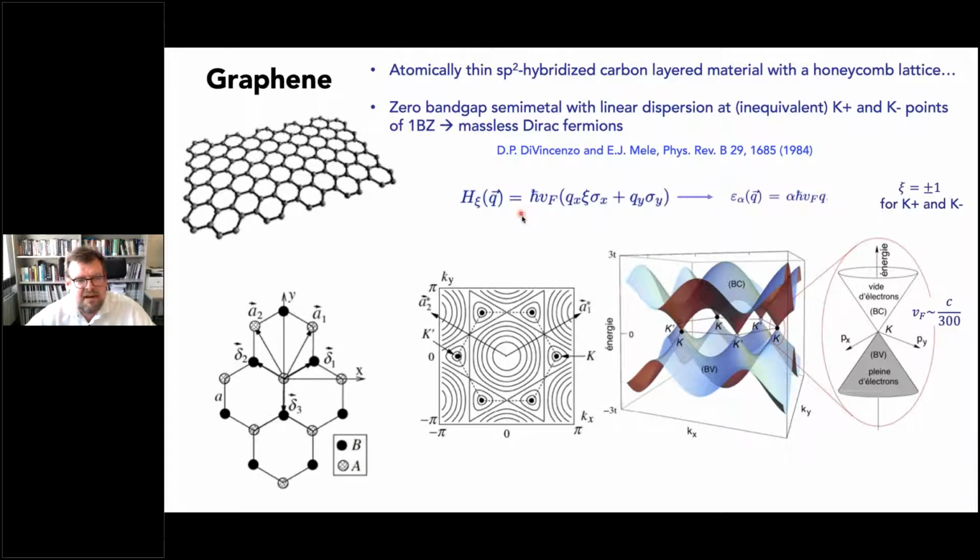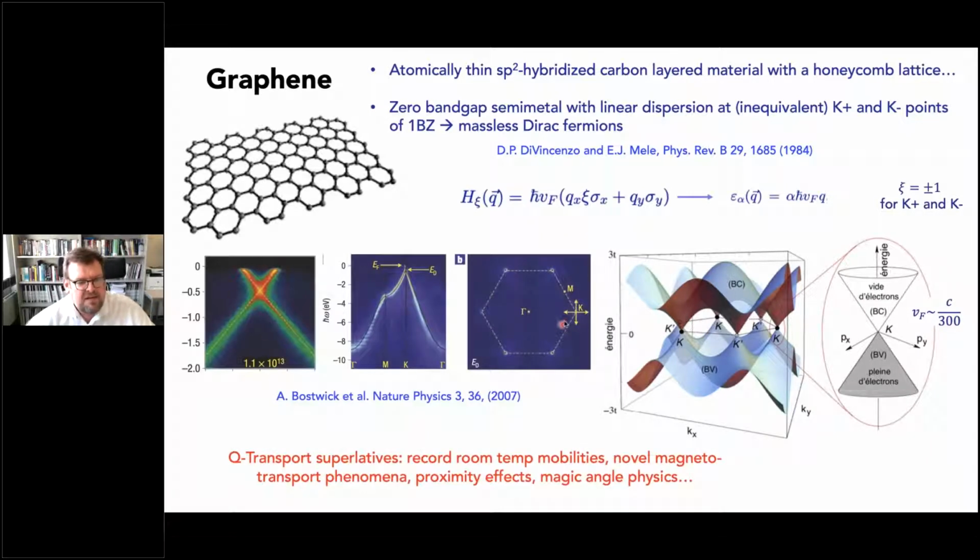So my message is graphene is a material with a very curious band structure, massless particles. Here, this has been euphorically confirmed by many experiments. I'm showing you here one of them. This is ARPES spectroscopy, showing measurements of the band structure. There you see the valence band just as it should be, sitting right on top of what you can calculate with tight binding theory yourself. And if you look at the vicinity of the Dirac point, that's this point right here, you see beautifully that essentially you have this linear dispersion relation.